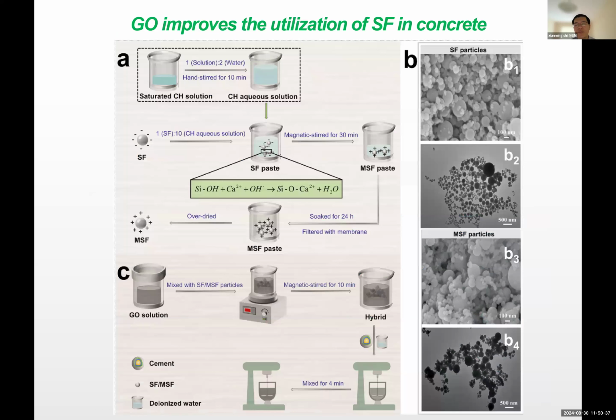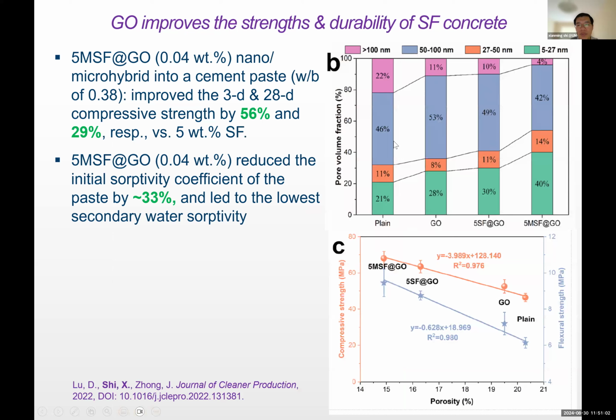So starting from the first example, silica fume. The challenge we ran into here was that the silica fume surface is negatively charged, so we cannot easily use graphene oxide, which is also negatively charged, to treat its surface. How we make that happen is we first treat it with alkali, a calcium hydroxide solution, so that we make the surface positively charged, and then we treat it with the GO ink. And the main results are pretty fascinating, because again, the use of graphene oxide is only 0.04%, but the modified silica fume is about 5%. In this case, you improve the 3-day and 28-day compressive strength by 56% and 29% respectively, compared with the 5% silica fume without the graphene oxide treatment.